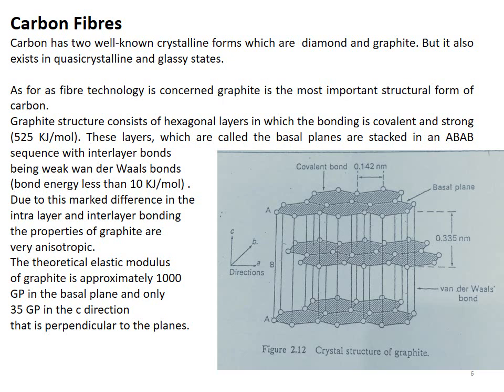So the theoretical elastic modulus of the graphite is approximately 1000 gigapascal in the basal planes and only 35 gigapascal in the C direction, as shown in this figure through these axes. That C direction is actually perpendicular to the basal planes. It means within the basal planes it has very high strength, and across the basal planes, at an angle of 90 degrees to the basal planes, their strength is very low.